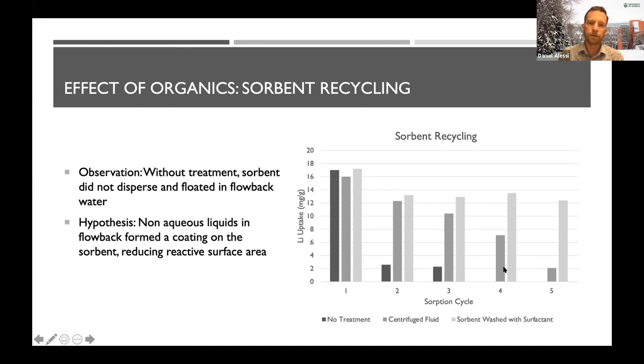So what we did to test the organics hypothesis ultimately, and you can see we had success here, is washing it with a surfactant. So this is a detergent, essentially, it's a soap. The one we use is called Triton. It's an industrial surfactant. And again, you get the same recovery in the first one, 16, 17. It does decrease in the second cycle down to 13. But again, if we wash between every single step, every one of these cycles we did a wash, you stabilize your recovery around 13 milligrams per gram. So the message here is that if you have a petroleum brine that has significant organics in it, you're going to need a washing step between cycles in order to keep the DLE material effective at recovering lithium.